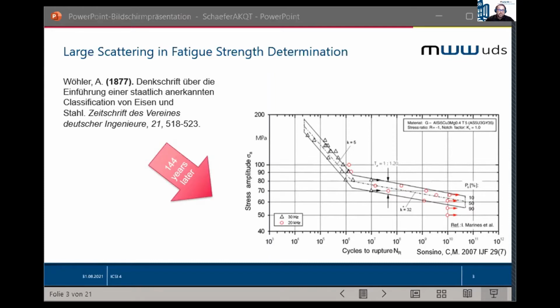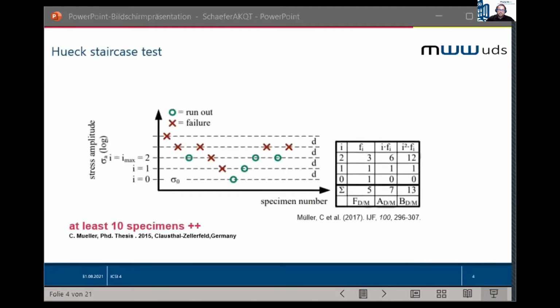So some materials have a fatigue limit of 2 million load cycles, some of 10 million load cycles, and for FCC materials, no one really knows. It depends on the size of inclusions or the mechanical contrast between inclusions, maybe billions of load cycles. And for the fatigue strength, different methods have been proposed and discussed, such as the maximum likelihood method or the Hück method, and they all have in common that at least 10 specimens are needed to get just the mean value of the fatigue strength. Up to 50 are needed for the scattering bands, and due to the large scattering, fatigue strength testing results in very high cost, and you all know that, in high testing times, even with resonance testing systems.